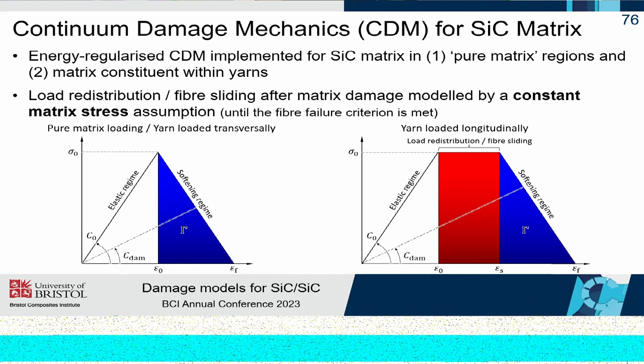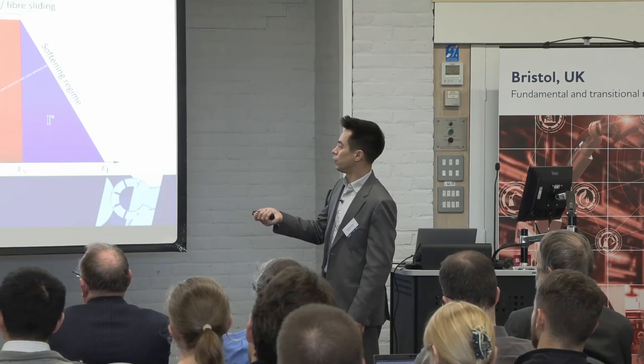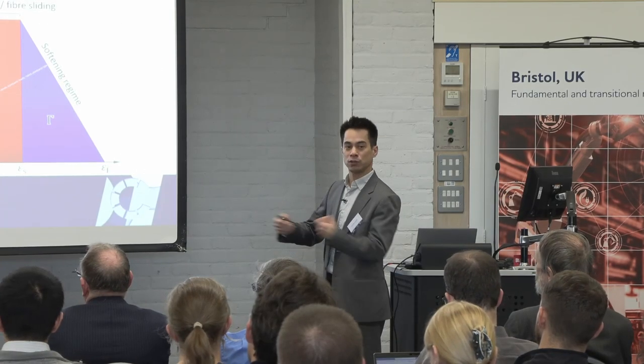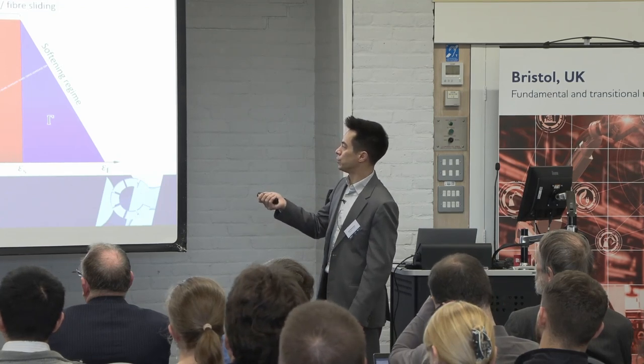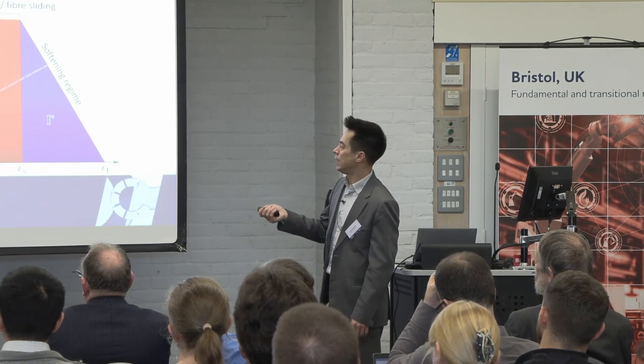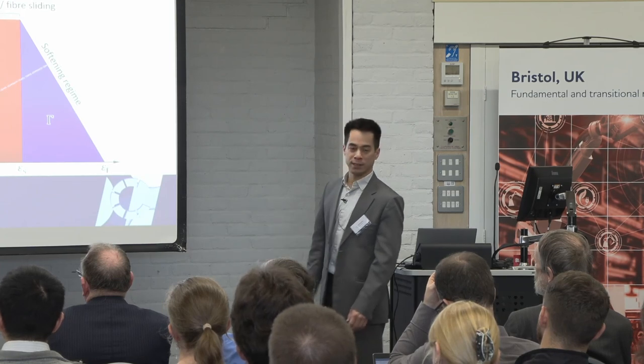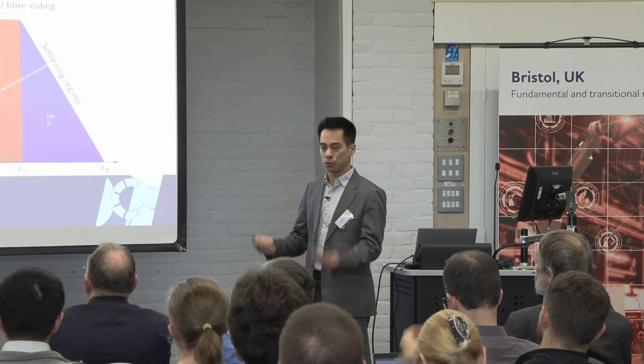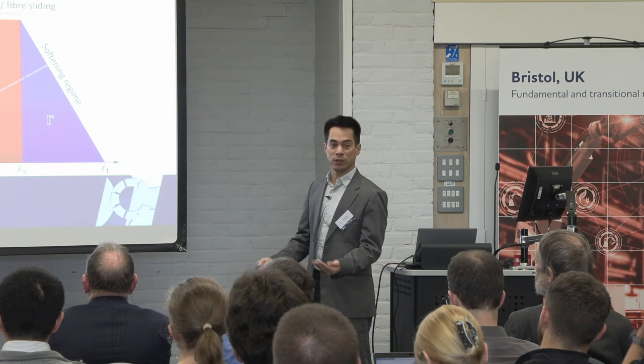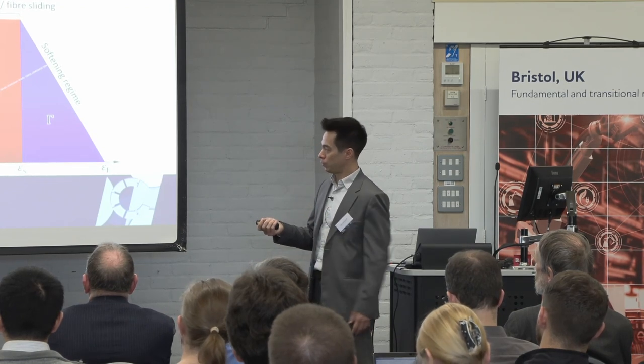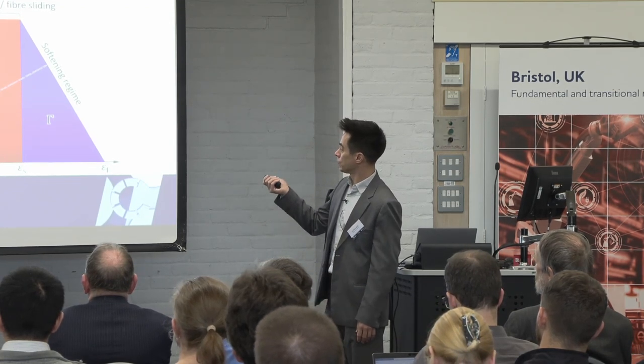And so if you were to plot the stress strain response of that material, you would see for pure matrix or for the yarns loaded transversely, you would see an elastic regime and then a softening regime. And the area highlighted here is related to the energy released when you fully fail that portion of material.